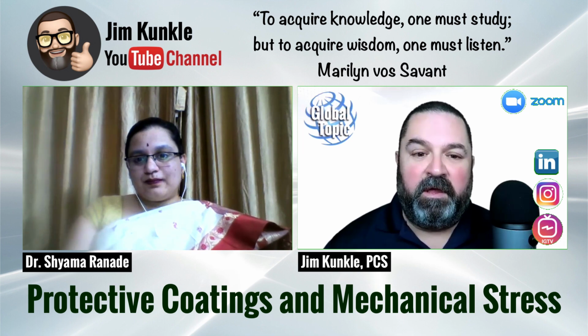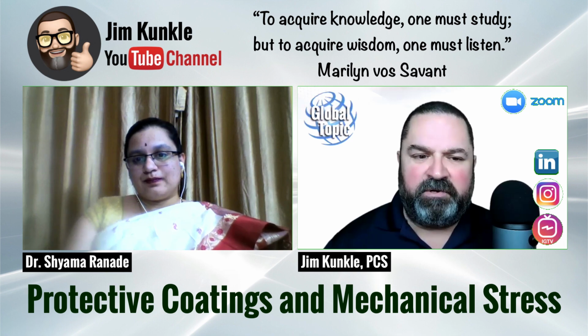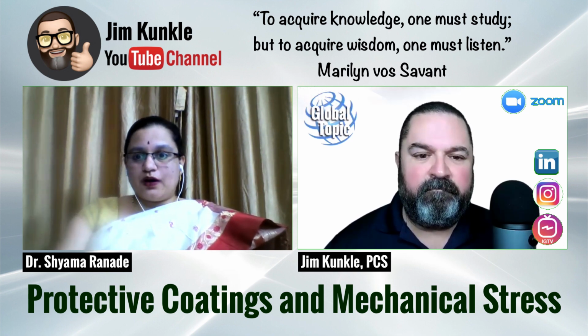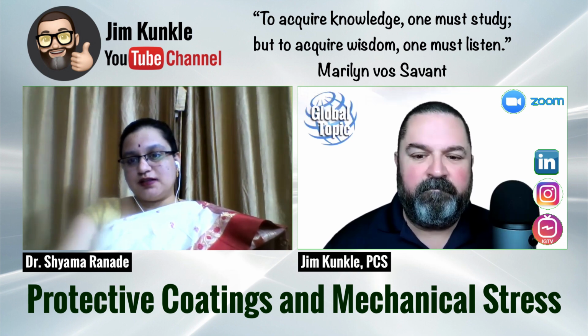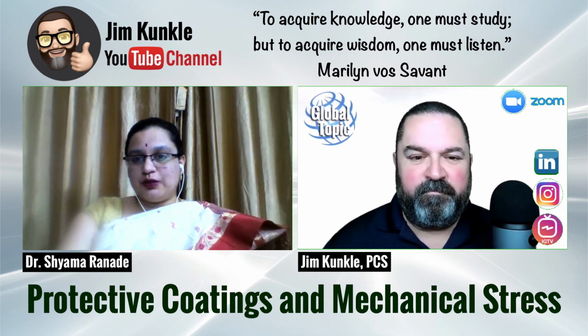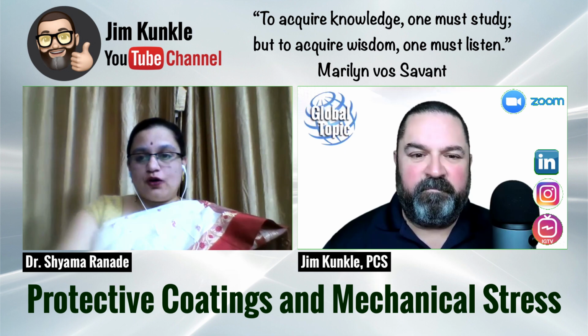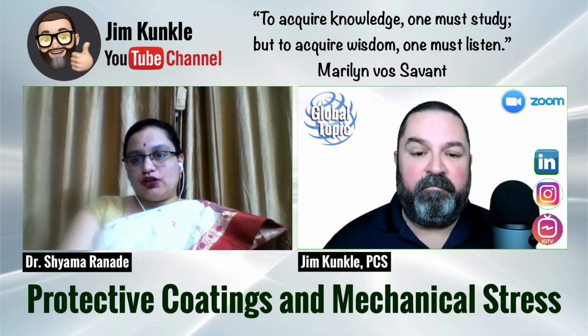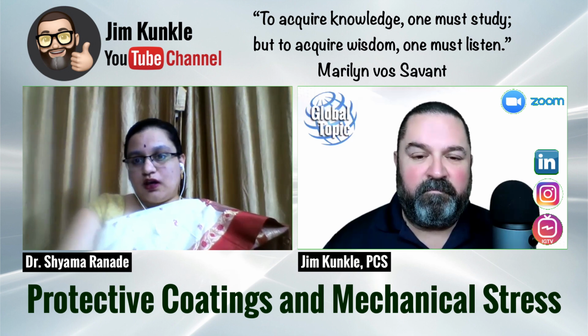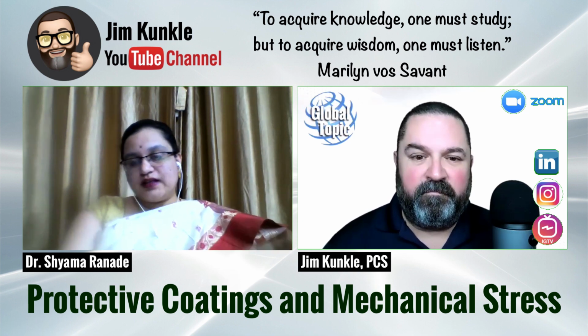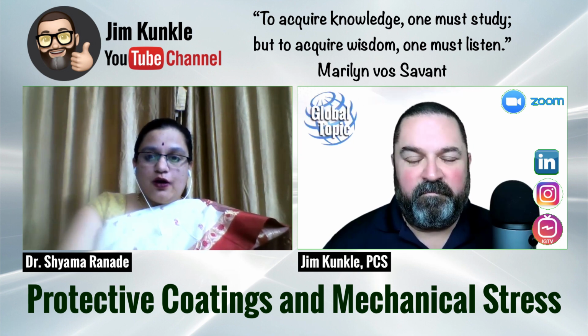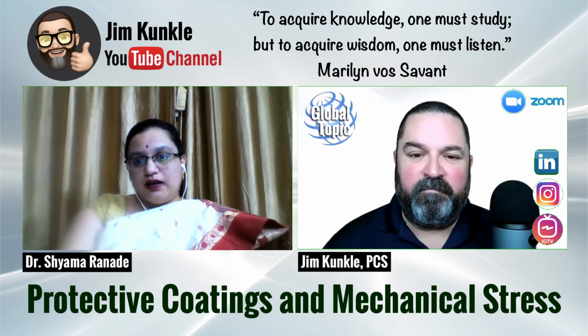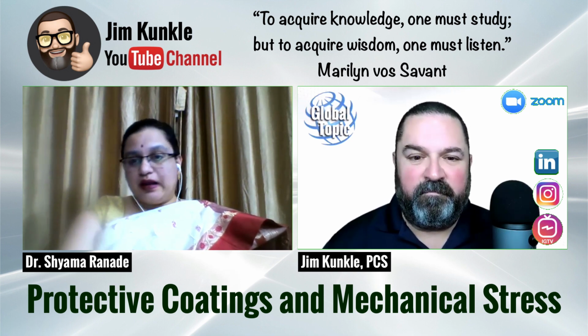As a published author in Progress in Organic Coatings, you, along with two other industry experts, published an article on coating degradation of epoxy coatings. Could you cover the critical elements of your published findings? Sure. I did my work as a PhD student with the Australian Energy Pipeline CRC, and I was fortunate to work with esteemed industry people and excellent advisors. We focused on the effect of mechanical stress and cathodic protection on coating degradation. This paper specifically focused on mechanical stresses in the very low plastic region, which usually takes place in pipeline hydrotesting or in usual pipeline procedures like bending and horizontal drilling.